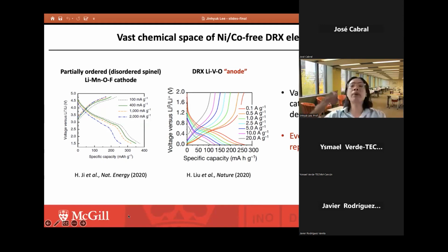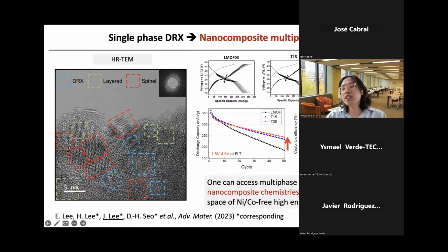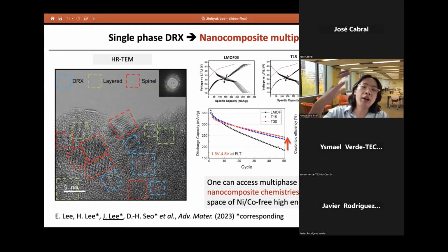So I would like to say that the chemical space of these disordered oxide materials is very, very large. In fact, it is so large because instead of sticking to the single phase compound, we found that we can make these DRX materials into nanocomposite multi-phase heterogeneous compounds to further expand the chemical space and achieve higher specific capacity and higher capacity retention. I'm not going to go into detail because the time is ticking too fast, but instead of staying in single phase, we can move on to the multi-phase chemical space to achieve very high capacity. So there are a lot of exciting new opportunities on this material.